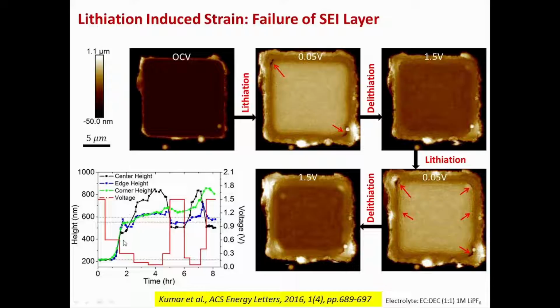We use a 0.6 volt hold, and then we go to lower voltages and hold till lithiation is complete, and then we delithiate, and then follow it for the next few cycles. For this study, we have used an electrolyte which is EC:DEC and 1M LiPF6.